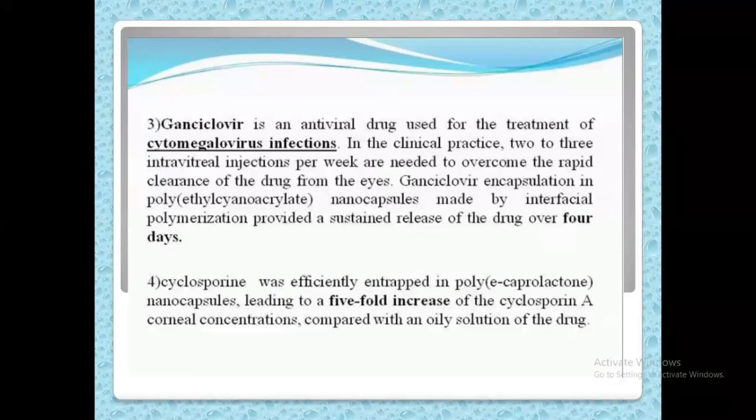So ganciclovir encapsulation in polyethyl cyanoacrylate polymer nanocapsules, made by the interfacial polymerization method, provided a sustained release of the drug over 4 days. Similarly, cyclosporine, another drug, was efficiently entrapped in poly-epsilon-caprolactone nanocapsules, leading to a 5-fold, that is 5 times, increase of the cyclosporine corneal concentration.